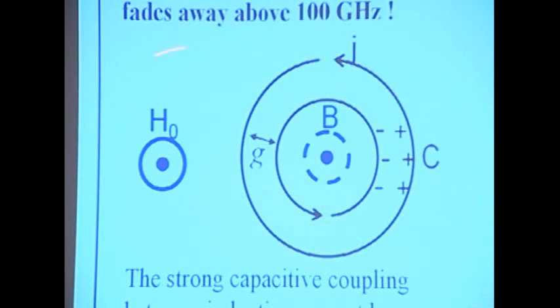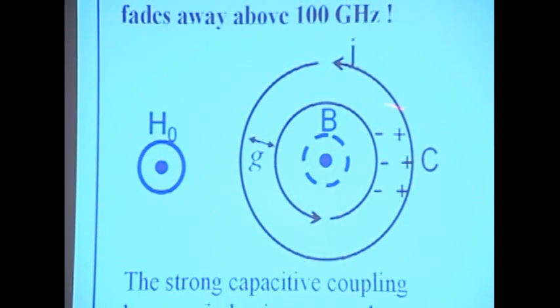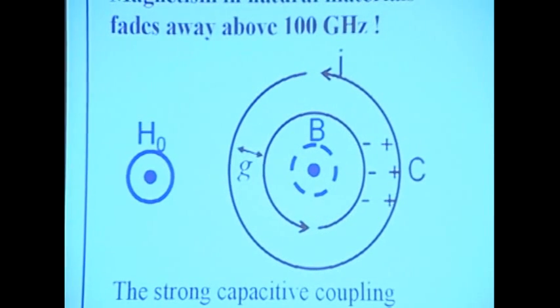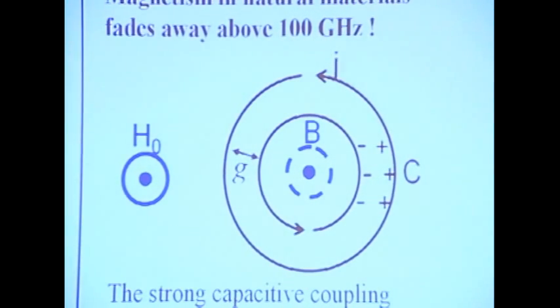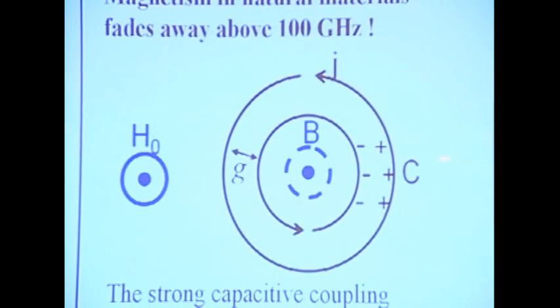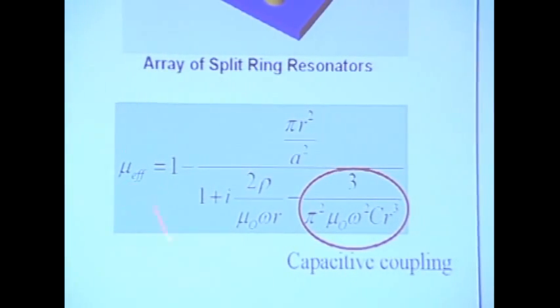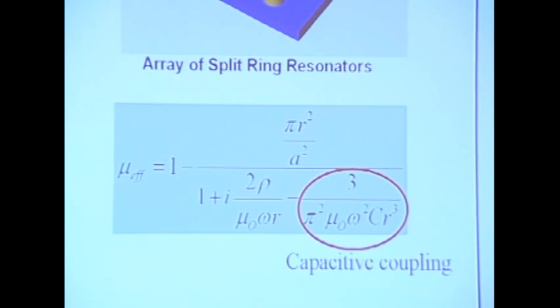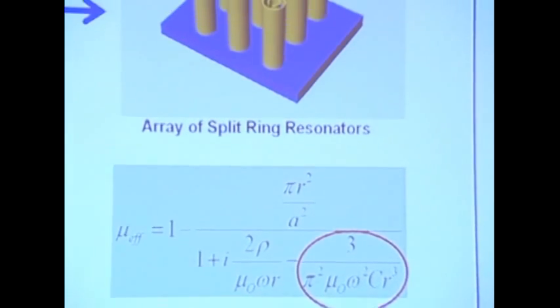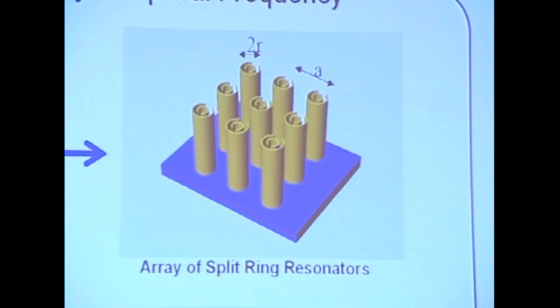That resonance gives you an overall magnetic field around this entity that can be larger or lower than the excitation field. So you could have a paramagnetic or diamagnetic response. And this can be simply calculated with an effective property. Again, in photonic crystals, you cannot ascribe this effective property, while in metamaterials you can, because you make sure the size and also the lattice distance are much smaller than the wavelength. So when you excite with an electromagnetic or optical wave, as long as the lattice size is much smaller than the wavelength, you can view that as a homogeneous response.